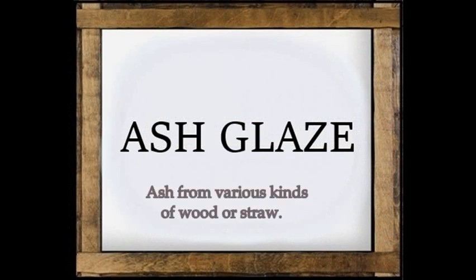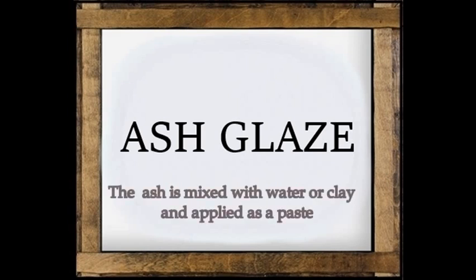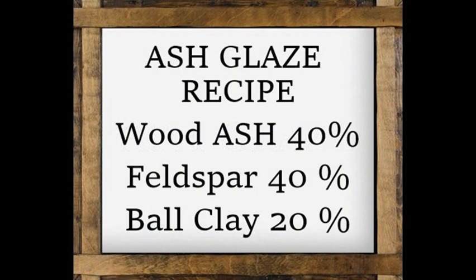Ash glazes are ceramic glazes made from the ash of various kinds of wood or straw. Ash glazing began in China after the accidental discovery that the ash from the burning wood was causing the glaze. So they started to add ash to the glaze before the pot went into the kiln. Ash glazes have historically been important in East Asia, especially on Chinese, Korean, and Japanese pottery. The ash is prepared and then it is mixed with water and often clay and applied as a paste. A basic recipe would look like this. Wood ash 40%, feldspar 40%, and ball clay 20%.